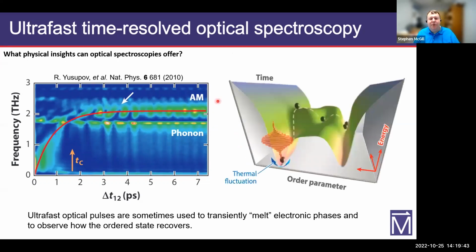And so just as an example, we can chart the free energy landscape versus the order parameter, let's say, on the axis represented by the charge density wave. Maybe there's a sample where you have a charge density wave that's competing with superconducting order. Well, if we imagine the ultra-fast time along this axis and energy along this vertical axis, then the optical excitation pulse can come in. It can change that energy landscape. The position of where we are in that is represented by this ball. That can change. We're now in a different phase, and we can fall into different local energy minima that otherwise would not be accessible.